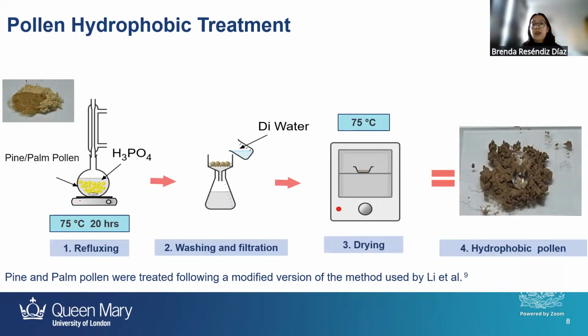And then you can observe here the hydrophobic pollen. From the picture, you can see that there is a yellow pollen and it starts absorbing water immediately when I was placing a water droplet. But after this treatment, where we remove all these proteins, it starts to turn more hydrophobic.